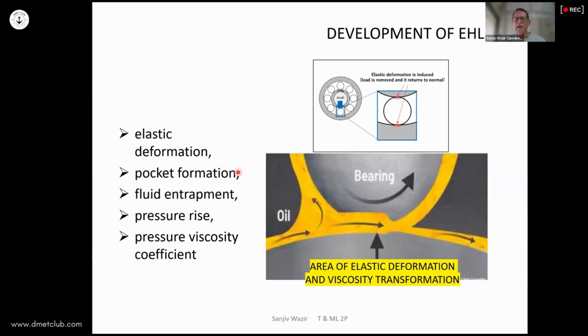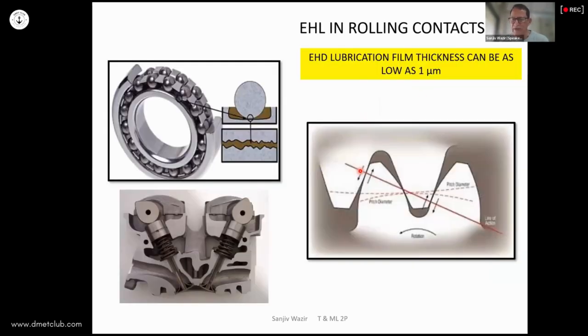And if that deformation results in some kind of a pocket in which oil gets trapped, and then that entire load is passing through that small pocket, load is very high, pressure increases, and then that pressure viscosity coefficient comes in, and that oil starts behaving more like a semi-solid. At that point, at that time, that oil is behaving more like a semi-solid, which prevents metal-to-metal contact taking place, and provides lubrication at that point in time. So that is elastohydrodynamic lubrication. Of course, it can't be very thick because the oil will spill out if it was too big, and that pressure rise would not take place. So usually it can be as low as 1 micron, but max goes to 10, 12 micron or something like that.